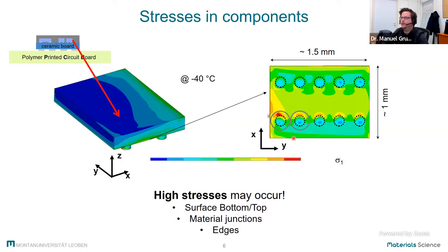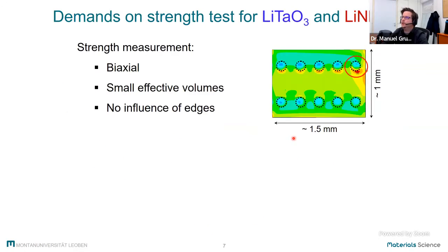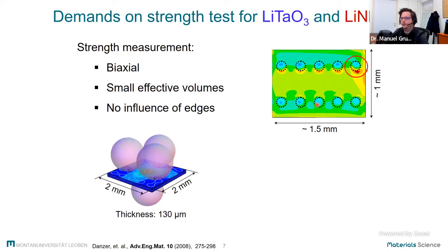Okay, now we had a first impression of the stresses that can occur, and we wanted to look at the strength of the material so we can see at which point fracture can occur. So we were looking for a testing device with rather similar stress distributions. So biaxial stress fields, small effective volumes activated, and for the beginning, no influence of edges. And there we found this ball on three ball test where we did our first mechanical characterizations.